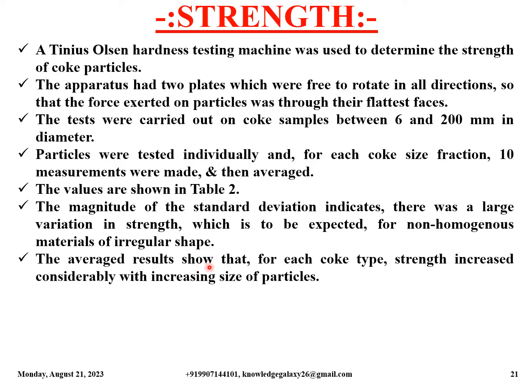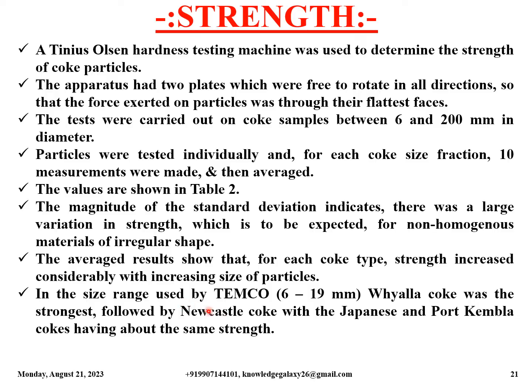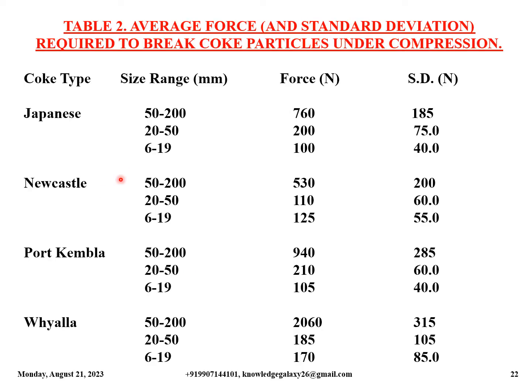The averaged results show that for each coke type, strength increased considerably with increasing size of particles. In the size range used by TEMCO, that is 6 to 19 mm, Whyalla coke was the strongest, followed by Newcastle coke, with the Japanese and Port Kembla cokes having about the same strength. So this is the table which shows the average force and standard deviation required to break coke particles under compression. You can pause this video and observe the table contents.